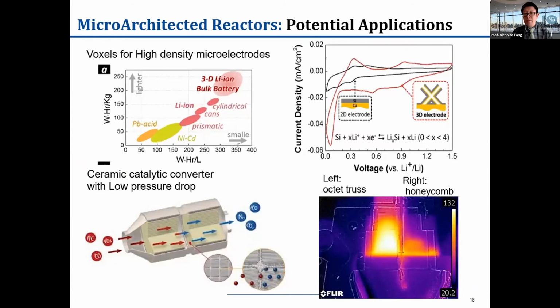And this architected material is not only important for implants or scaffolding for tissues. We are also actively looking at its potential use in, for example, microarchitected reactors. So on the top, what I'm showing is the high density microelectrodes that show promise to increase the energy density and power density beyond what is currently generated using the layer by layer approach, for example, for lithium ion batteries. Our preliminary results already show that a factor of 6 improvement can be achievable simply by changing the electrode orientation into the 3D lattice domain.